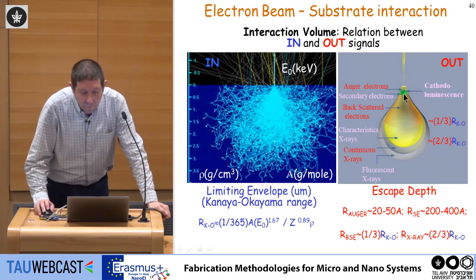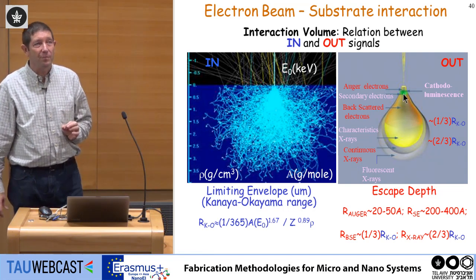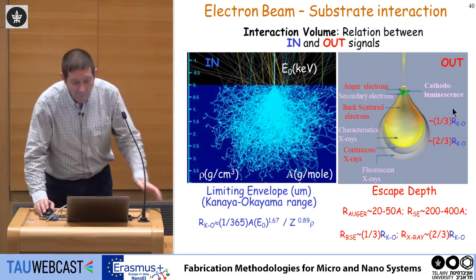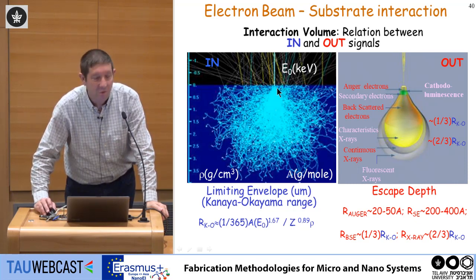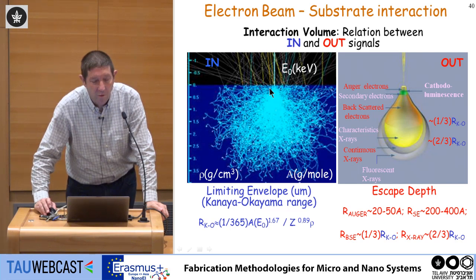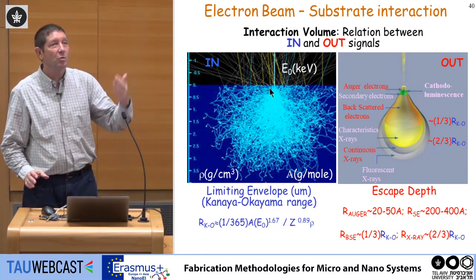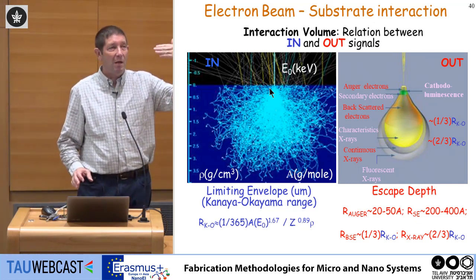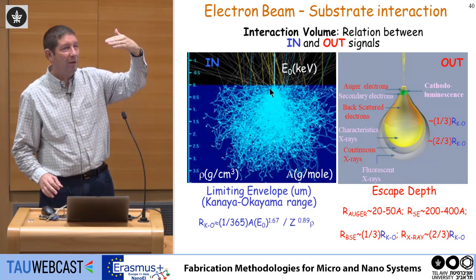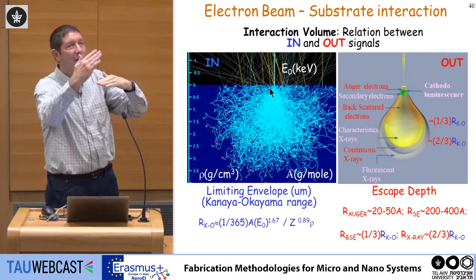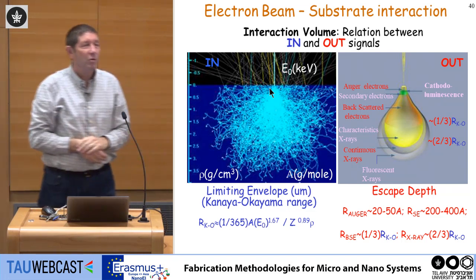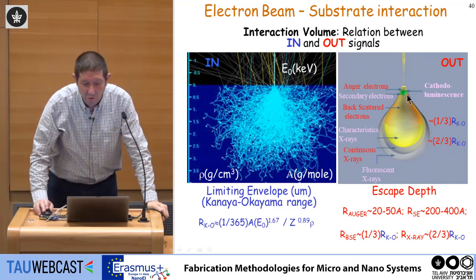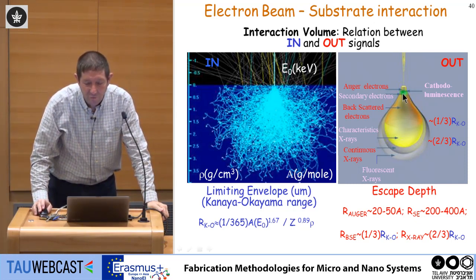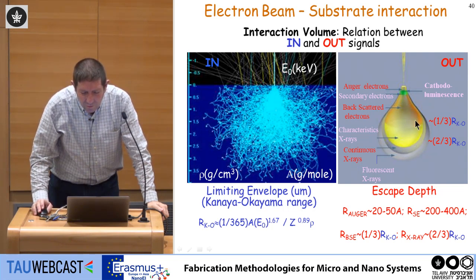So the Auger electrons are very low energy. And because they're very low energy, if you have an Auger electron emitted here, it does not reach the surface. So only Auger electrons from this region. Auger electrons are electrons which are emitted due to the Auger interaction. Auger interaction is when you have a high energy electron at a high level going down and giving its energy to another electron which is emitted. So this typically is a low energy process. So these Auger electrons are detected from a very, very small volume. The backscattered electrons are emitted from a much larger area, and the X-ray is emitted from a very large area.